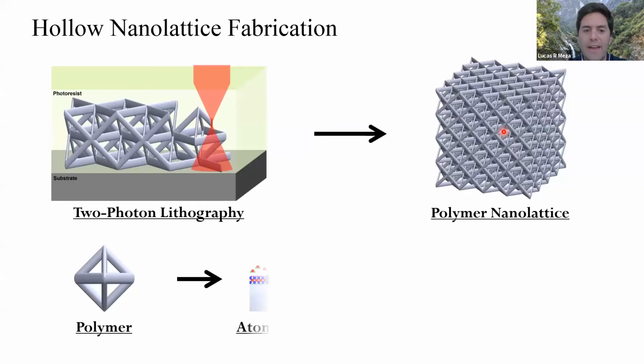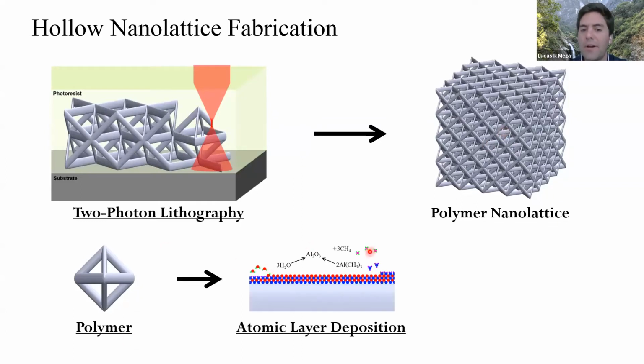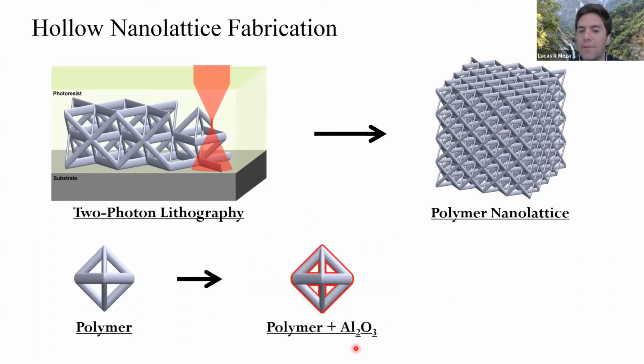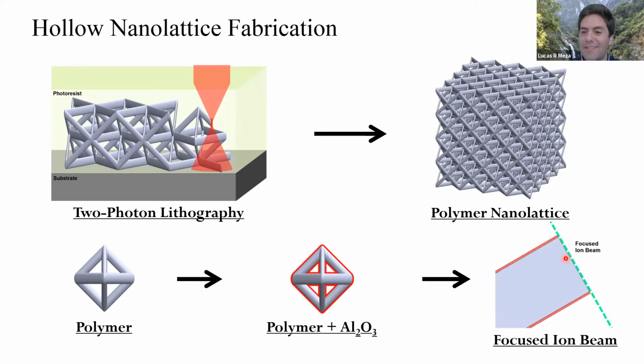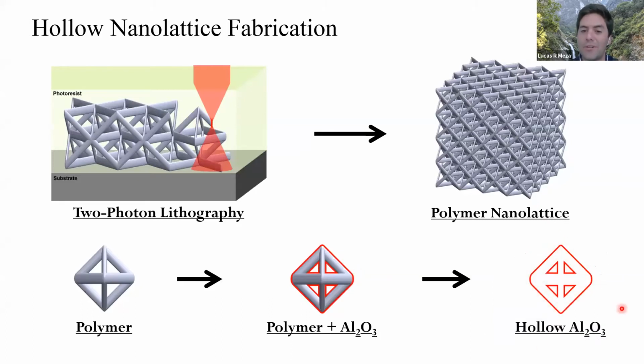In that coating process, you take a polymer and use a thin film deposition technique such as atomic layer deposition to coat it with a thin layer of something, in this case aluminum oxide, because you can ALD any material as long as it's aluminum oxide. We take that aluminum oxide, use a focused ion beam to narrowly expose the edge of the material, use an oxygen plasma to burn it out, and we end up with a hollow structure. So I'll show a few videos now on these hollow alumina nanolattices and what their properties are.